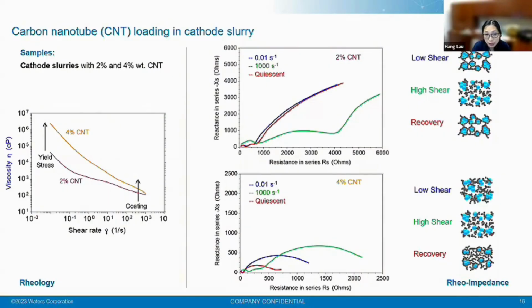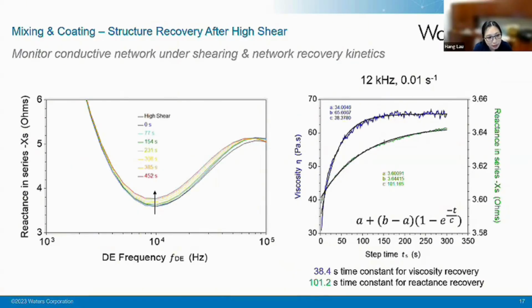Of course, you're seeing different resistance of the material itself. So the formulation will be different, but you can also see that the recovery is different. They did not go back to the initial recovery. So that's very important for understanding the recovery behavior. And this is a snapshot of the recovery step. You also need to understand it's time dependent, as we showed earlier. The conductive network also has time dependent behavior that we can monitor with the real impedance. After shear breaking down, looking at the recovery, you can continue monitoring those.